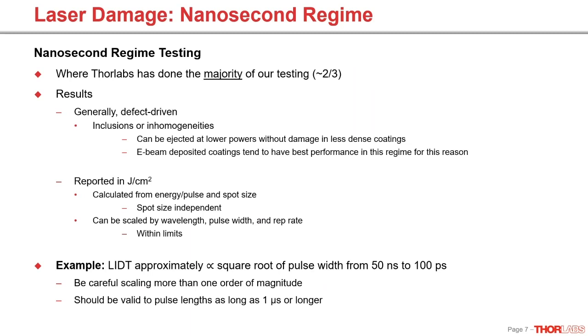So these inclusions or inhomogeneities can be ejected at lower power occasionally without damaging the coating if the coating is not particularly dense. So for this reason, you tend to get the best results in the nanosecond regime from electron beam deposited coatings because they're dense enough to give you good uniformity and a repeatable performance, but they're not as dense as some of the sputtered coatings. So you can eject the material from them without having that nodule blow out or cause a major issue. These results are reported in joules per centimeter squared, and that's calculated from the energy per pulse of the laser as well as the spot size.